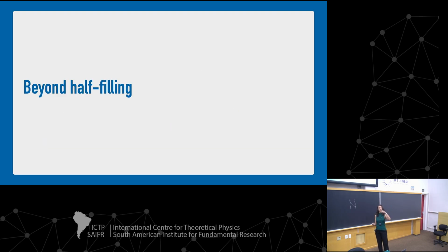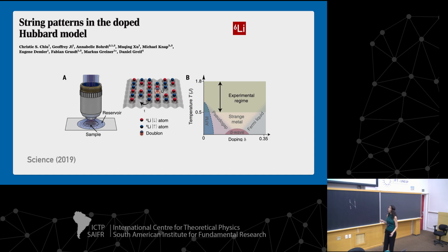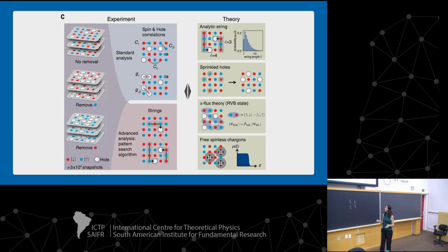And as I am talking about removing some atoms of the lattice, which is going beyond half filling, there are many experiments. I'm going to show only a few of them, but I selected two because I think they are really interesting. The first one of them shows string patterns, and this is very interesting because, at least to me, this is not something we do in condensed matter theory, but as they can do this and photograph different ensembles, they have many images, and they can try to use some sort of advanced pattern analysis to see something we would not see in a real material. So they have taken pictures and removed it and seen where the holes sit, and they found different patterns.